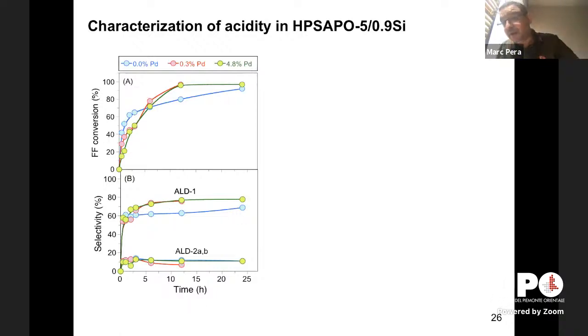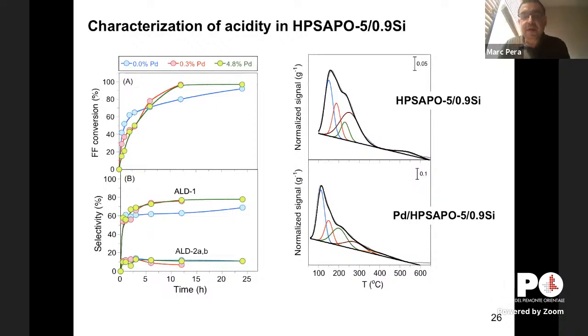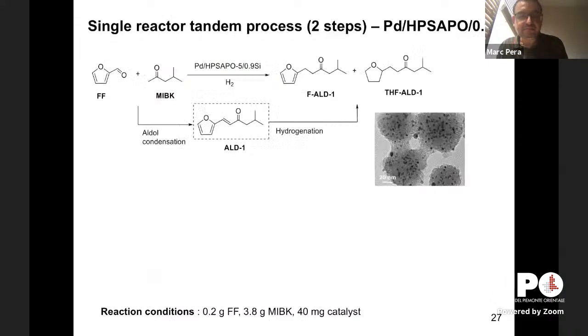So the fact that we put palladium in the form of palladium oxide, because it's not reduced so far, doesn't affect this aldol condensation. More or less, we see a similar pattern in terms of the ammonia TPD, with sites of intermediate strength in this zone here, and more or less the same pattern in the low temperature region. Now let's design this single reactor process.